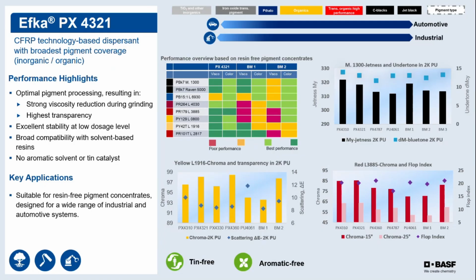And for red L3885 on the bottom, I mentioned earlier, we have organic pigments that need to be transparent so you can see effect pigments through that. So here we have a demonstration of that, with 4321 being the second set of data in this chart. You can see it has excellent chroma, both at 15 and 25 degree, and a very high flop index when let down with aluminum flake. So I hope I've made a very good case for 4321 being one of the highest order dispersing agents for excellent appearance in coatings. Back to you, Louis.